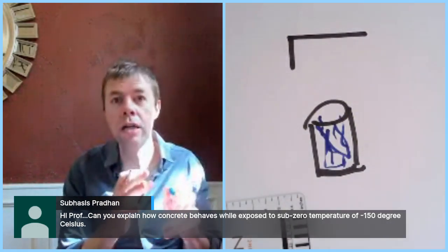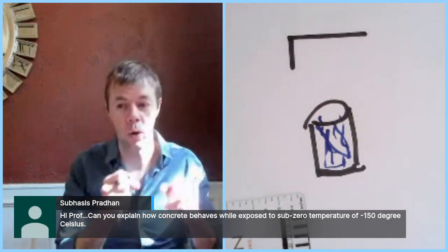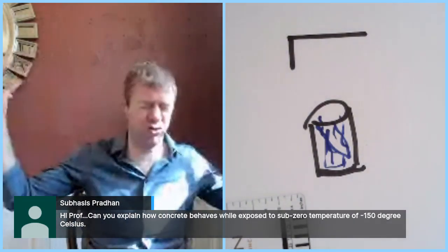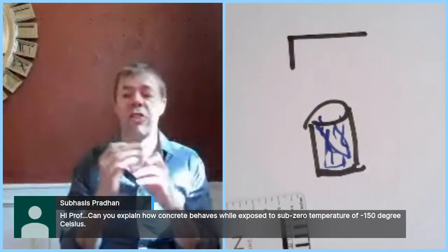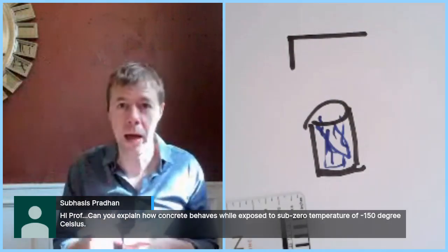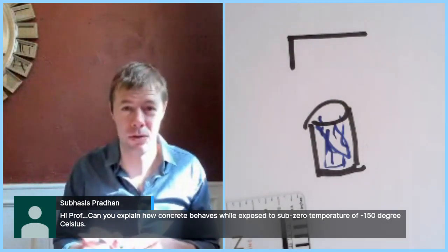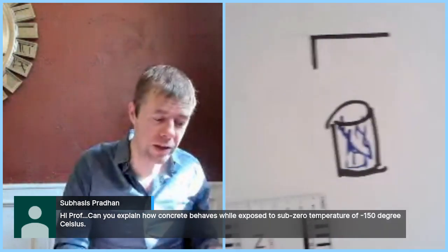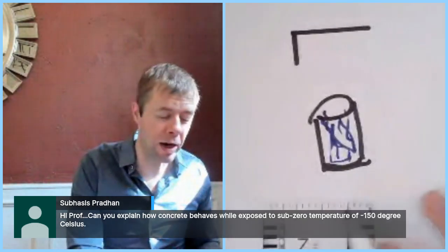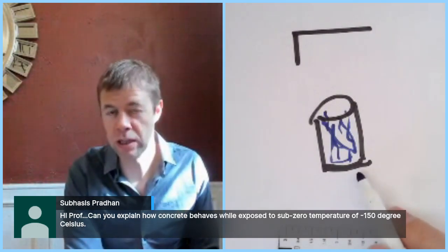I mean, it was unbelievable. Like the machine, when the concrete broke, it was explosive, like things going everywhere. I mean, it was unbelievable how it broke. I think it increased the strength by about, I think, three times, something like that. And so this idea, talk about a very inexpensive way to increase the strength of your concrete.